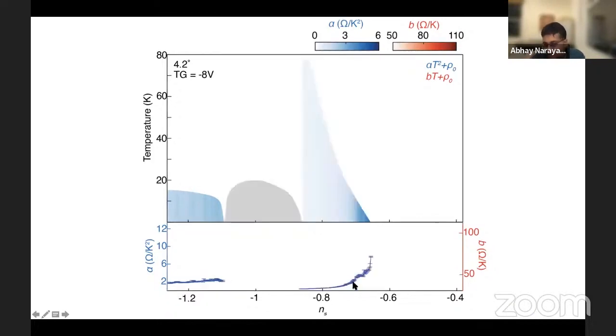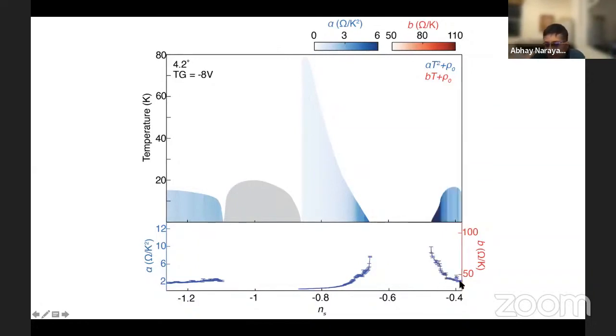But as I approach this quantum critical point, this coefficient really diverges by about 2 orders of magnitude. And at the quantum critical point, this becomes large, bounded by disorder. And similarly, if I approach the quantum critical point from the other side, again, I see this strong enhancement of this T-squared coefficient, which corresponds to a collapse of the Fermi energy as you reach the bottom of the band.